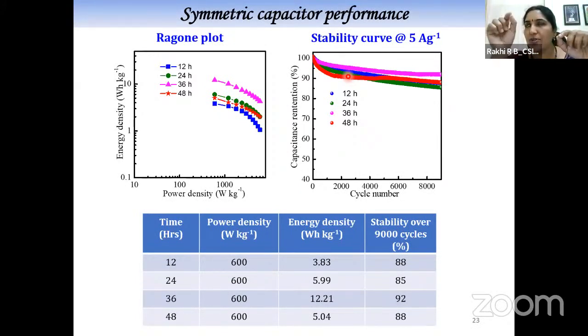In the direct growth, each electrode material is having direct contact with the conducting electrode material. So there is a conduction pathway, lowering the resistance, and the 3D structure of the nickel foam offers maximum electrolyte accessibility, maximum exposure to the MoS2 nanowires, and maximum capacity contribution. One more thing I want to add: I have removed the contribution from the pure nickel foam from all these calculations, so you don't have to worry about it, which was very small. Then we performed the cycling stability. We found that our 36-hour grown sample gave a stability of 92% after 9,000 cycles, not 5,000 cycles. So it is pretty good, stable, and an excellent one.